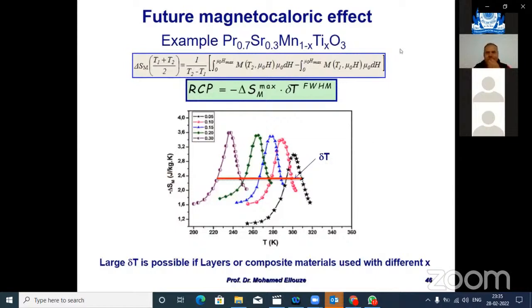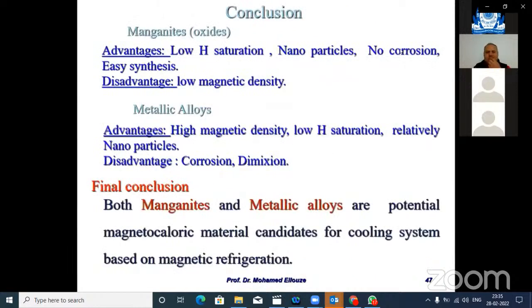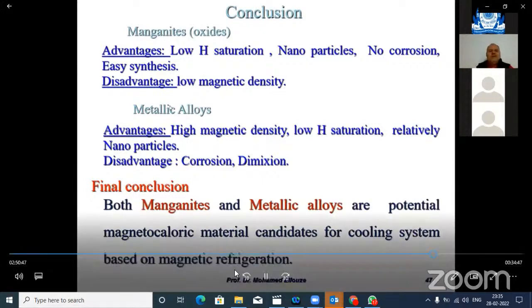So, to conclude: for the manganese oxide, we have some advantages. We have low saturation, nanoparticles are also observed, there's no corrosion, and it's easy to synthesize, though it has low magnetic density.